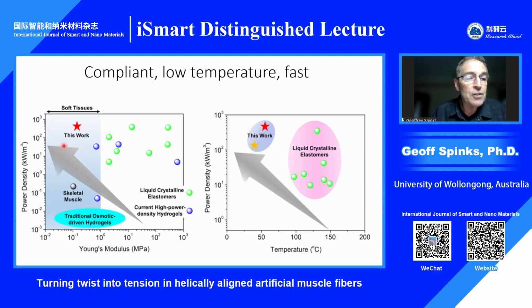And the other big advantage is that we were targeting a tissue-related Young's modulus. We were trying to match the modulus and compliance of soft tissues such as skeletal muscle. To do that, we had to use solvent to reduce the modulus. If we compare power density against modulus, you can see most other high power systems have considerably higher modulus, whether they're hydrogels or LCEs. In our work, we were able to produce powerful artificial muscles that simultaneously have really low modulus.